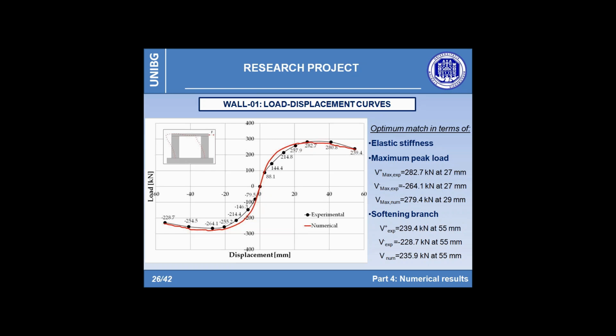The main differences are recorded with respect to the negative direction, but this evidence is only due to the cyclic effects. In effect, as you can see for each step of displacement, the experimental forces in positive direction are higher than the equivalent in the opposite side. This behavior is consistent with the Bauschinger effect that implies a reduction of the yield strength, inverting the verse of the imposed displacement.